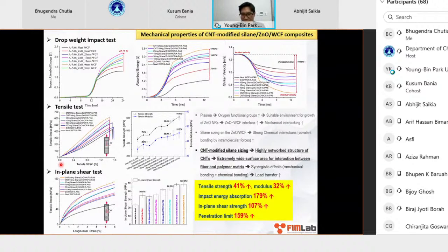And finally, from my perspective as a composite engineer, I want to show how all of these transition to the mechanical properties. So in terms of the drop weight impact test, tensile test, and in-plane shear test, which are all very important properties measured for composites, which are intrinsically anisotropic materials, the tensile strength and modulus increased by 41% and 32%. The increase in these performances is based on the reference material where there was no silane treatment, no plasma treatment, no CNT, and so forth. And we had a very high enhancement in impact, a 179% increase in in-plane shear strength, and also penetration limit. So we were very, very excited to get these results.